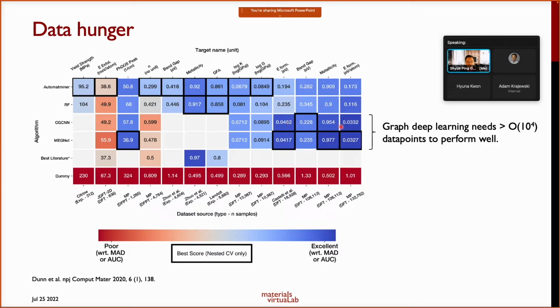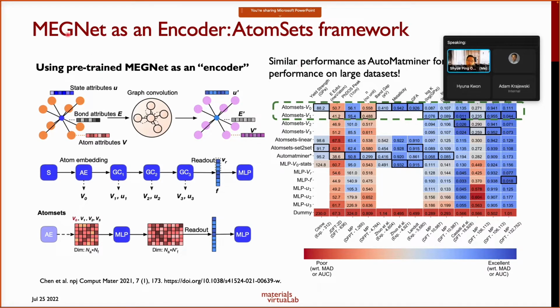Where the graph deep learning models, things like CGCNN and MEGNet, really come into play is when you have fairly large data sizes to train the model, and in those cases, they perform significantly better than your other machine learning models. Okay. Now, we decided that, well, it's well and good that you can use something like AutoMatMiner to try to predict properties at small data sets, but this is not ideal, right? As I mentioned, something like AutoMatMiner usually doesn't have structural features, and we really want to distinguish between polymorphs of materials. So we decided to come up with a way to solve this using graph deep learning, right? And what we did was to use MEGNet as an encoder.